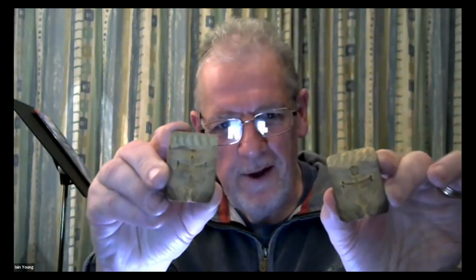And I'm going to touch on cleaning up patterns that have been through. Well, I might as well do it now. Natural rubbers. We looked at the natural rubber. Actually, this is a Malcolm Stelfox mold here from early days. That's for a Great Eastern Sharp Stewart. But natural rubber, if a pattern has been used in a natural rubber mold, the platinum-based silicone rubbers will not set against the pattern. When you cut the mold open, you get inside of it, it'll all be just gummy around the pattern, which is not ideal. I found out by accident.